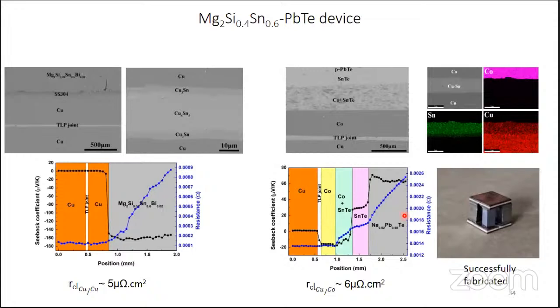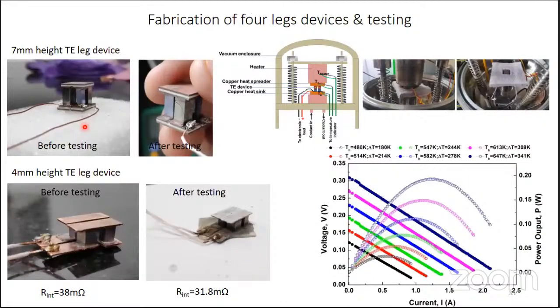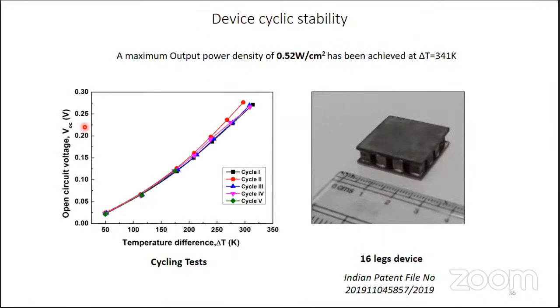And then we made appropriate contact and bonding techniques, and we were able to achieve very low contact resistance by manipulating these interfaces. And finally, we made small lab-scale testing devices, and we evaluated their performance. This is a 4-leg device, and this is a 16-leg device, and now a 64-leg device we have also successfully made. Effectively we have to optimize to get 128-leg devices. That's our ultimate target. Once we make it, we'll give it to industry for manufacturing.